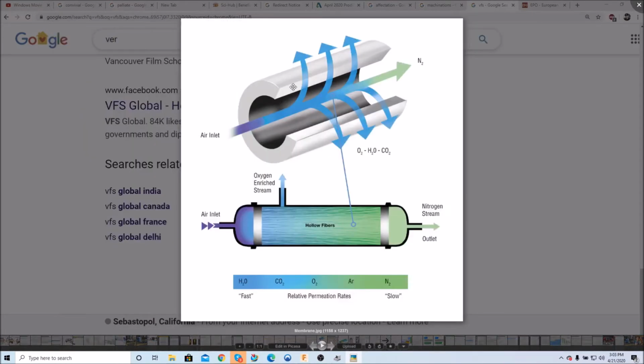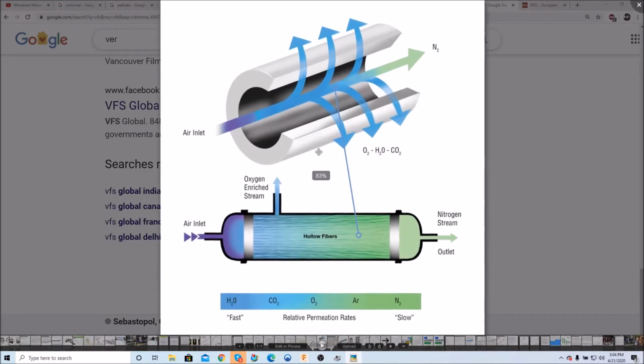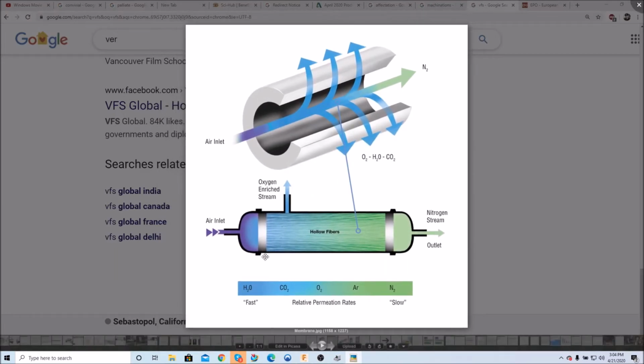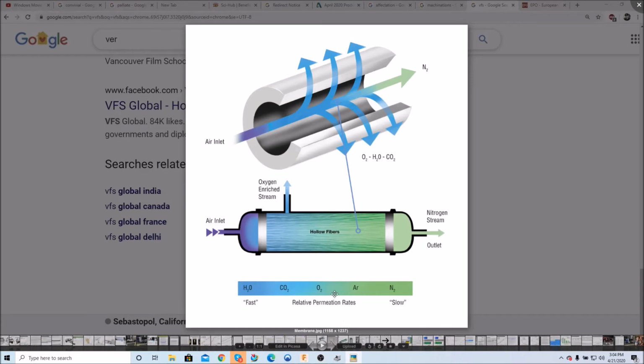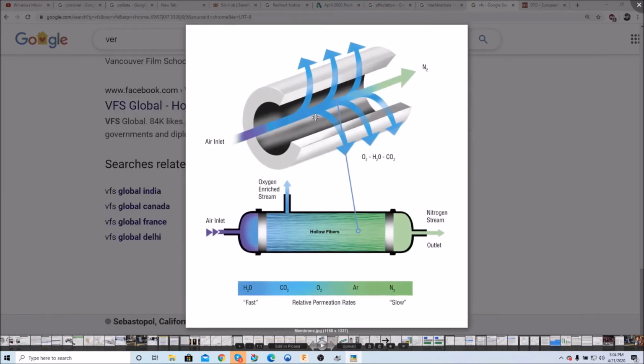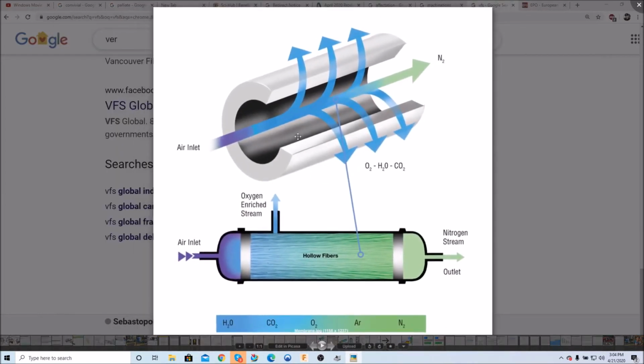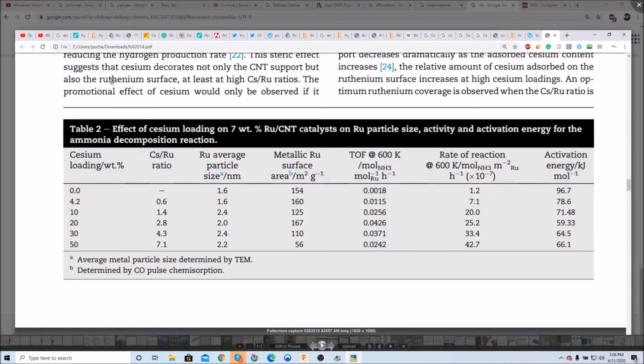Here's a membrane separator. We talked about membrane separators before we get into our fuel cell. Before we pass the gases into our fuel cell, we want to separate as much nitrogen as possible. And one of these small membrane separators that I pictured earlier can provide sufficient separation to get most of that nitrogen out and not impair the efficiency of the fuel cell. So again, the way it works is that you have gases. Smaller gases are going to permeate through the perimeter of the tube, and larger gases are going to continue flowing through the tube.